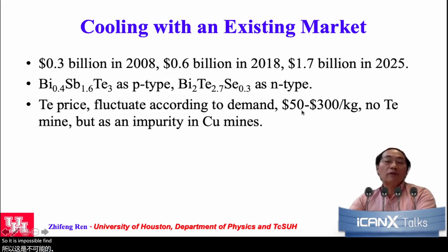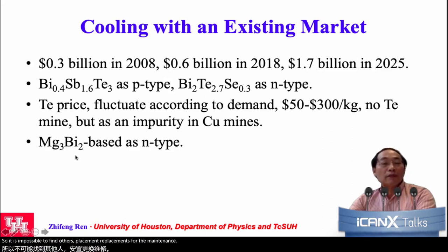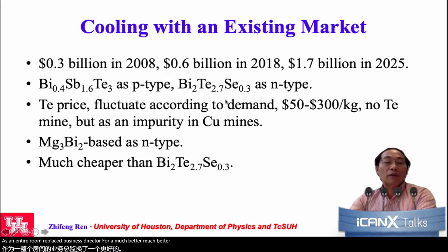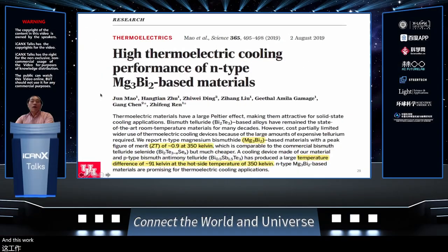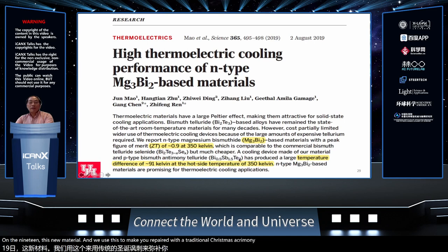So is it possible we can find other replacements to maintain the price? Yes, we did find magnesium bismuth, both elements are very abundant on Earth, and so the price is very low. As an N-type, it replaces bismuth telluride at a much lower cost. Okay, and this work was reported just a couple of years ago, in 2019. We used this new material paired with the traditional bismuth antimony telluride P-type. We generated a delta T of 91 Kelvin when the hot side is maintained at 350 Kelvin, which demonstrates and proves that this material can replace bismuth telluride as N-type.